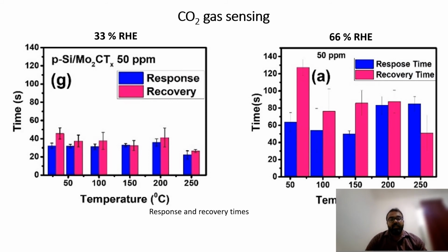So in this research we could successfully fabricate a sensor which works so fast, like it can detect the gas within seconds and recover within seconds. So this is a great achievement of our group for realizing a device like this. And in the case of high humidity, we observed that there was a delaying of the response and recovery. This may be due to the interaction of water molecules in the sensing mechanism.